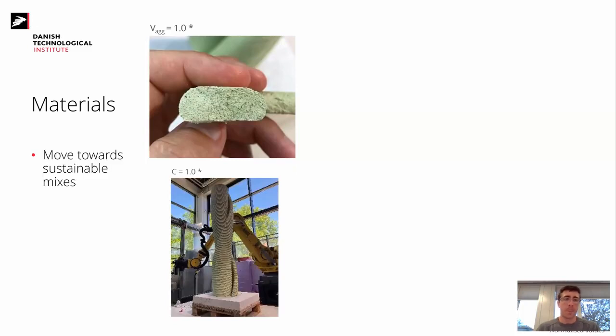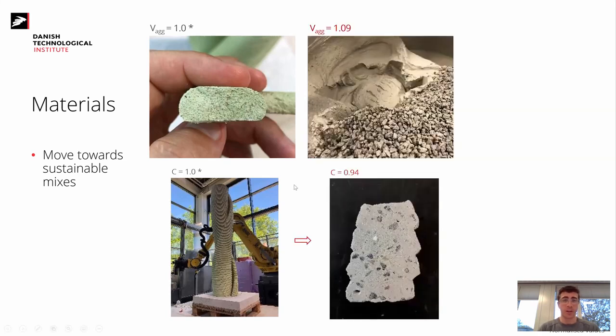So companies are moving from pre-mixed materials and mortars to more sustainable compositions that would be using concrete. And in the very first test we had here at DTI, all the numbers I'm showing here are normalized data, because unfortunately I cannot share the mix design. It's still confidential within the project we are running. So the picture on the left with the green mix, we have a material that is a mortar. This mortar uses white cement and some pigments. So I'm calling that number 1. So my cement content was 1.